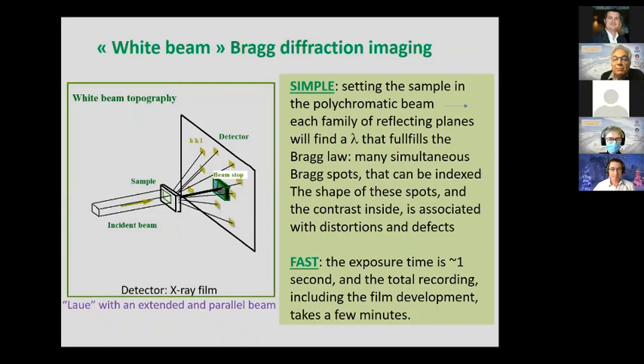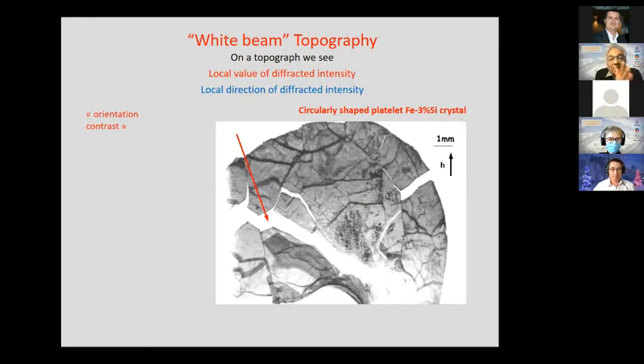The Bragg spots can be indexed. The shape of these spots and the contrast inside is associated with distortion and defects. Well, this is a very fast technique. The exposure time is of the order of 1 second, and the total recording, including the film development, takes a few minutes. You can say that this is a kind of Laue technique with an extended and parallel beam. White beam topography gives on a topograph the local value of the diffracted intensity